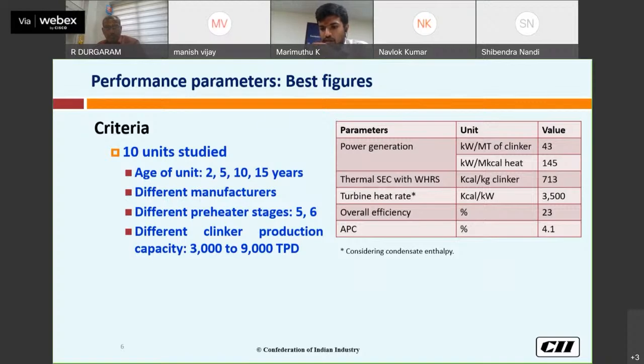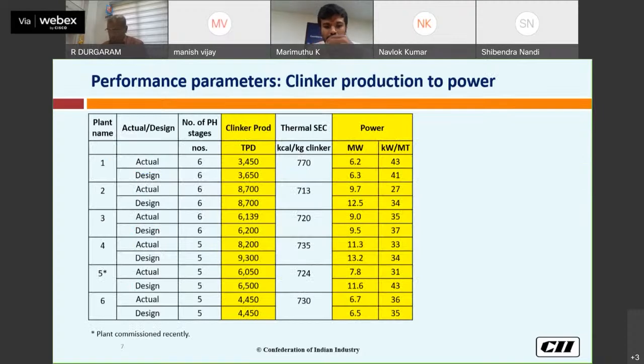Based on that, for power generation, the best figure which we have seen is 43 kilowatt per metric ton of clinker, and based on heat, 145 kilowatt per million kilocalorie heat. The thermal specification with the WHRS, the best which we have seen is around 713 kilocalorie per kg clinker, and the turbine heat rate best we have seen is around 3500. Overall efficiency of the system is 23, and APC is around 4.1%. This is the data which we collected from the 6 units.